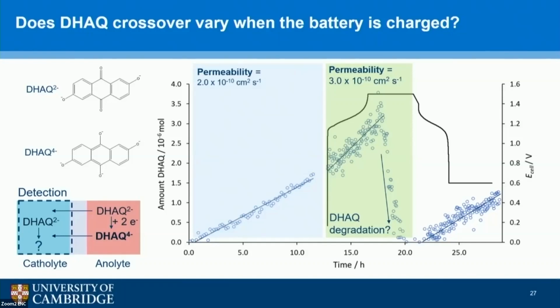And this is something that hasn't previously been reported in the catholyte side of the battery. And then finally, when we discharge back to the 2- state, we can then get a permeability again that's relatively similar to the initial permeability, which possibly further supports that migration is driving crossover during the charging step.